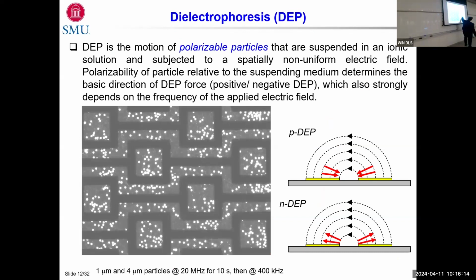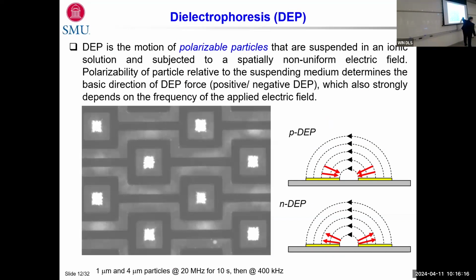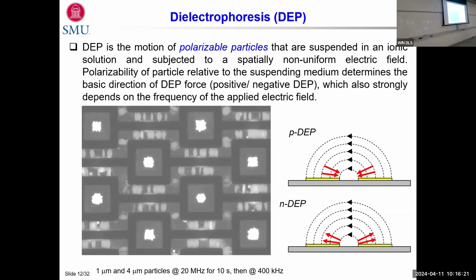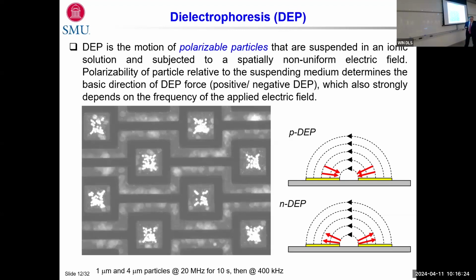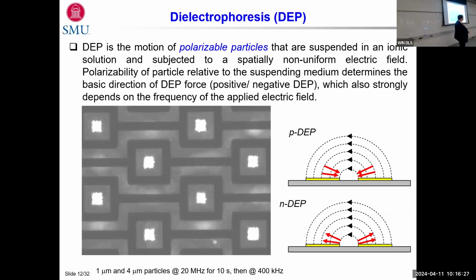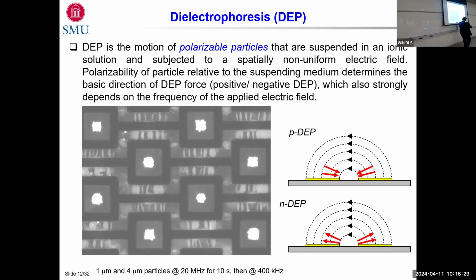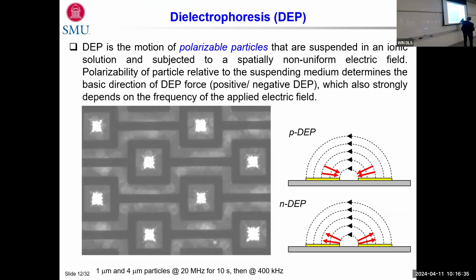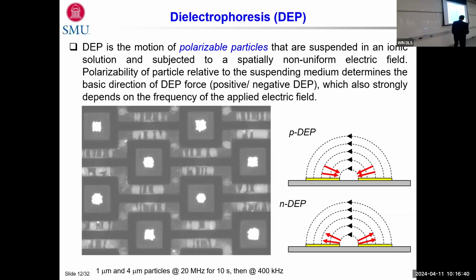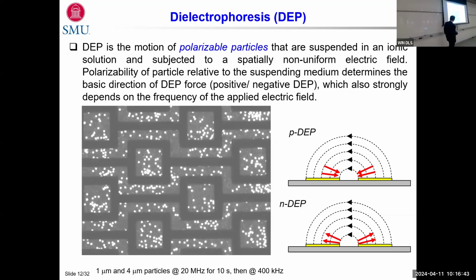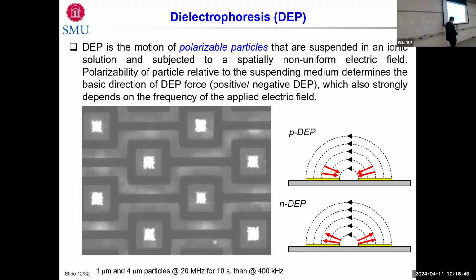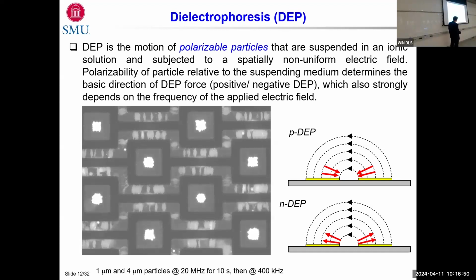If the particles are more polarizable, they will go to the large electric field gradient zones, and that's positive dielectrophoresis, which means that they will be stuck there. But negative dielectrophoresis is for particles that are not as polarizable as the media, and they will be repelled from these zones. If you push things away, you don't have control of it. If you capture them, you actually grab them, right? So basically, we see these two different effects. The movie shows real-time images of 1 micron and 4 micron particles, I think polystyrene, at first 20 megahertz for 10 seconds, then 400 kilohertz.